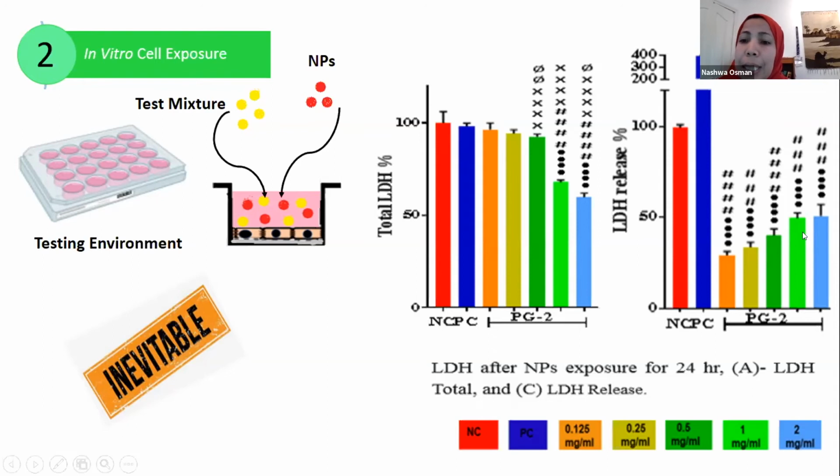When we did the release assay, with the same increase in concentration, at the highest two concentrations that we are seeing here, what we saw is a release of LDH, but nowhere near the spontaneous release of our negative control, the untreated cells. So here I immediately suspected these particles are interacting with the amount of LDH released in the medium.